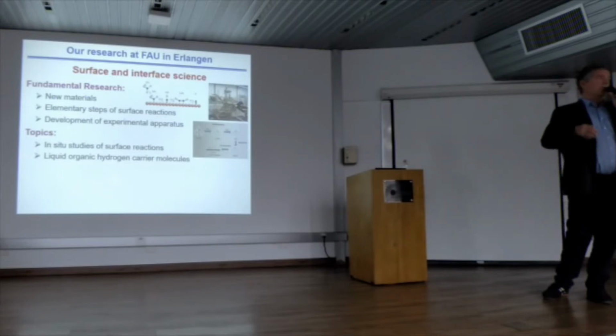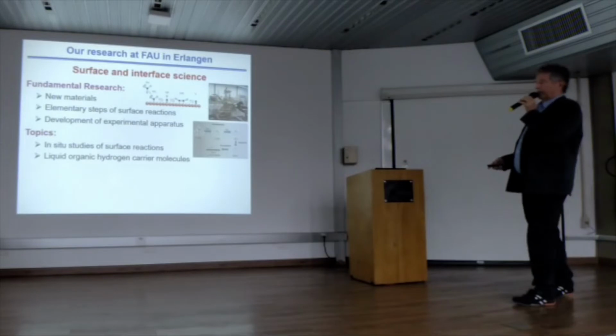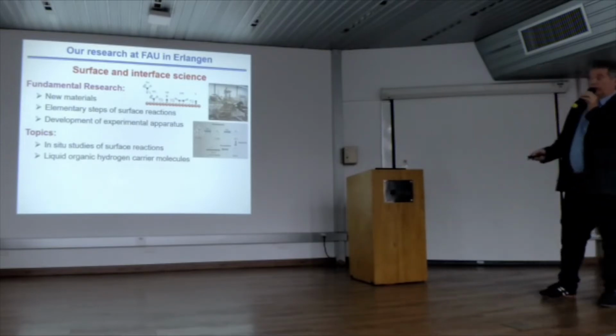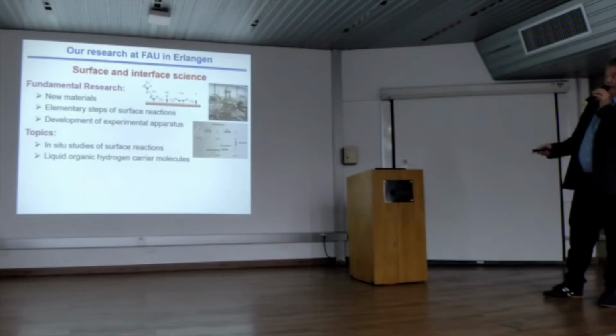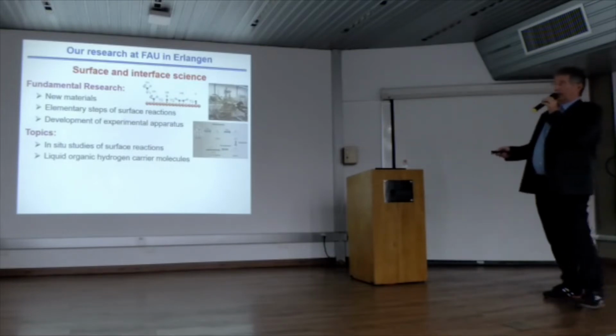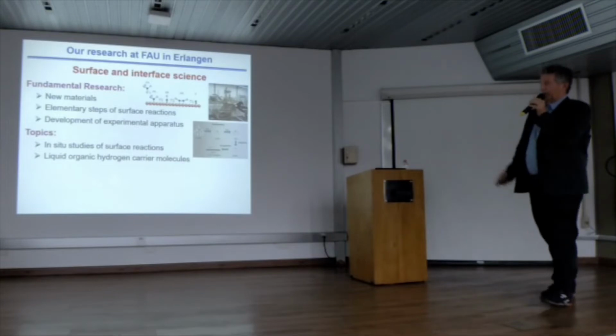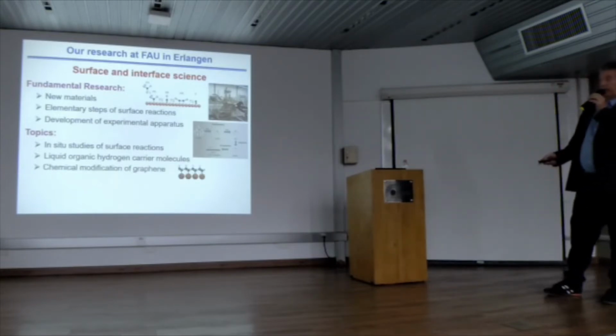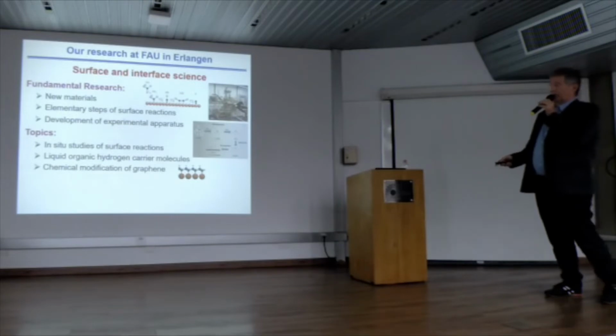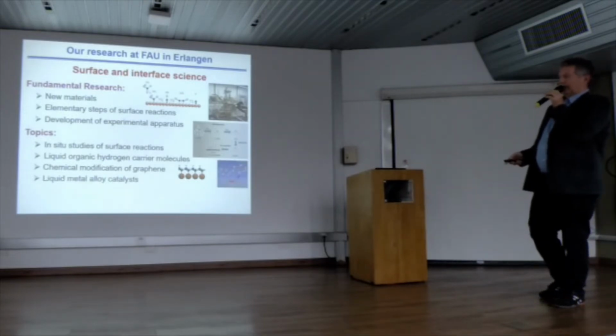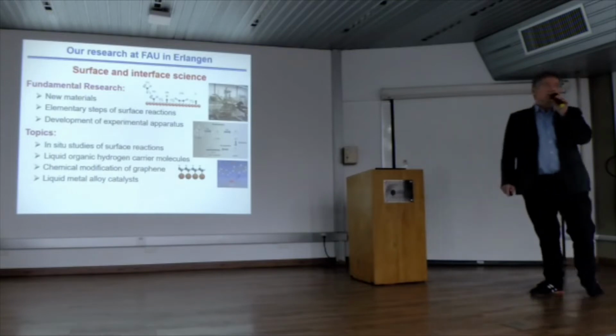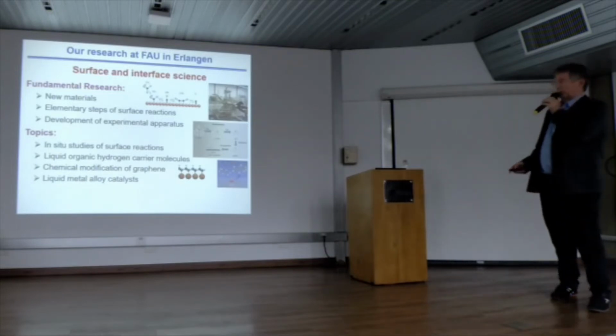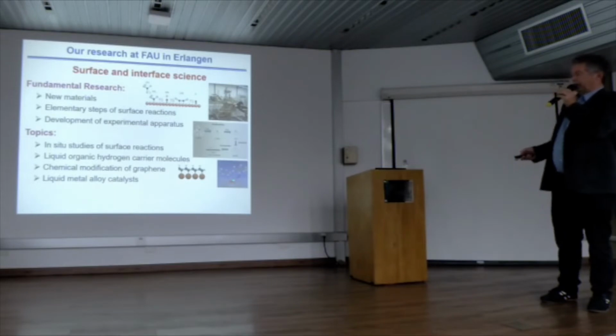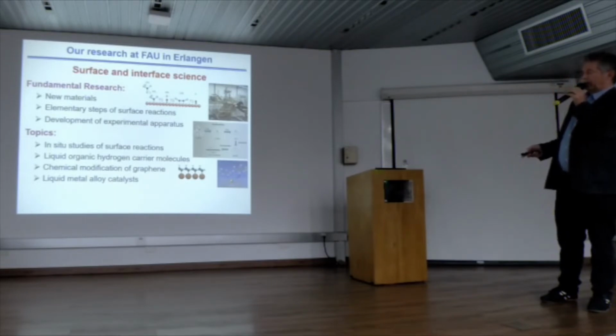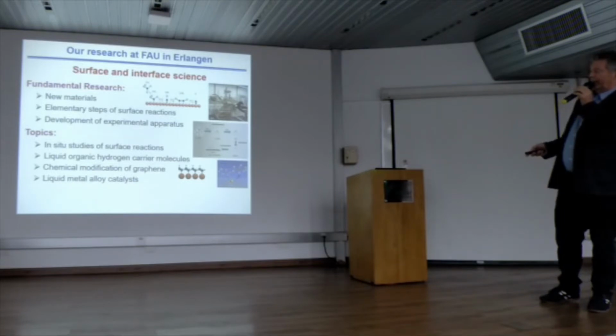The fuel cell then converts the hydrogen to electrical power. And our understanding is that what we contribute is doing model studies where we try to get the individual steps that you have in this type of reactions, also for these more complicated molecules. Then we modify graphene. So we somehow try to link molecules to graphene. We work with liquid metal alloy catalysts. These are very specific systems like platinum in gallium, where individual platinum atoms swim at the gallium surface for short periods of time. And then there are so-called single atom catalysts.